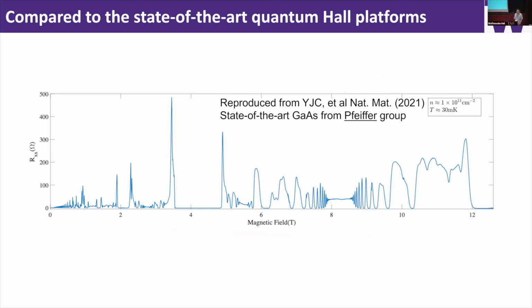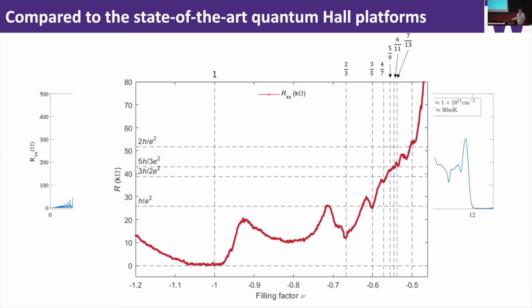And I just want to compare with the state of the art of a 2D electron gas. Right here, reproduced from a beautiful paper, is a 2D electron gas from gallium arsenide. In the measurement of Rxx, you can see there are many beautiful fractional states with this high mobility sample, with mobility probably on the order of 30 to 40 million. And this is our data, I would say pretty lossy compared to the previous one. We measure Rxx as a function of filling factor. We do have several states: 1, 2/3, 3/5, 4/7, 5/9, and so on.